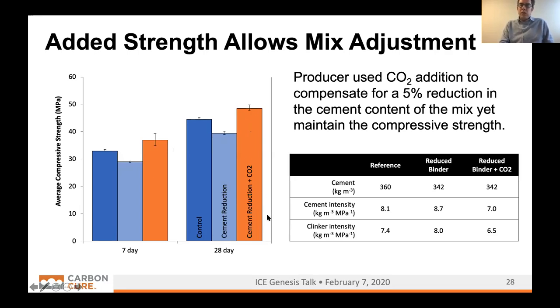So you can see on the right, we went from 360 kilograms of cement in a cubic meter down to 342, which is about 18 kilograms of cement that was removed, 5%. And we can look at it in terms of the strength provided by the cement. So you only needed 7 kilograms of cement to provide an MPa of strength in the reduced binder plus CO2 batch, and you needed 8 kilograms in the reference batch. So essentially, by adding the CO2, you've made the cement more efficient. You can provide more strength per unit of cement.